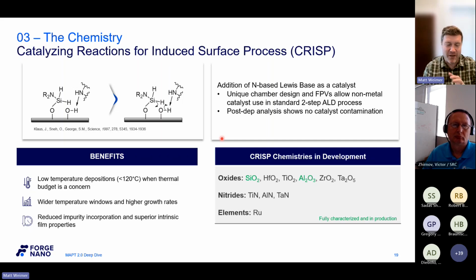One thing I didn't talk about that I'll briefly mention is we control our precursor introduction by pressure. We don't use MFCs. So if we have TMA, let's say the room temperature vapor pressure is 9 or 10 torr, we'll bring that down to 8 or 9, to 4 or 5. So we can further limit the number of moles into the chamber.